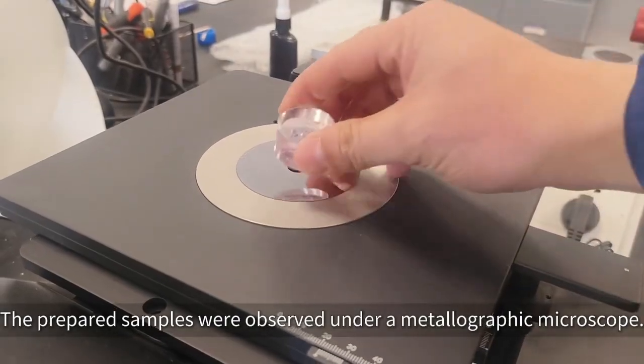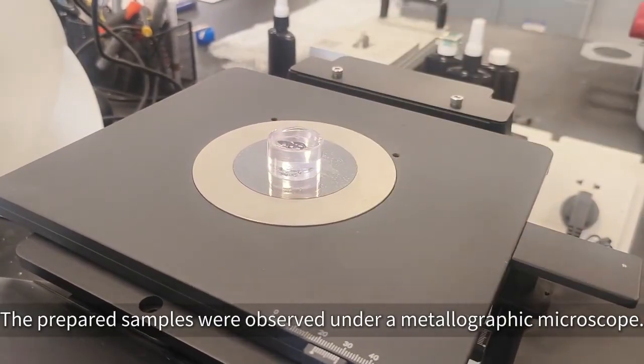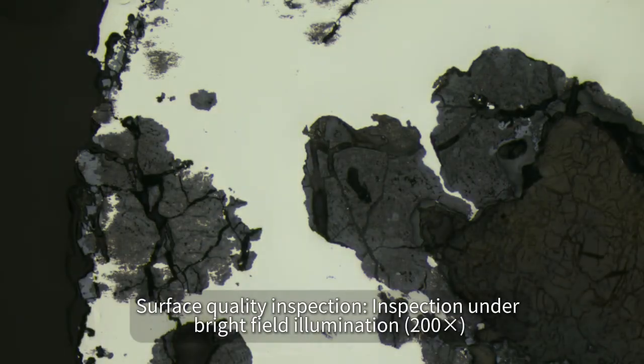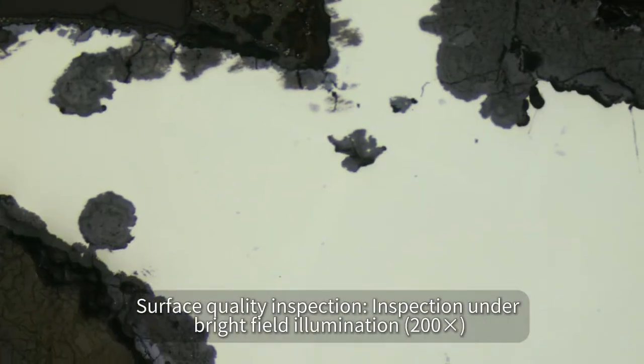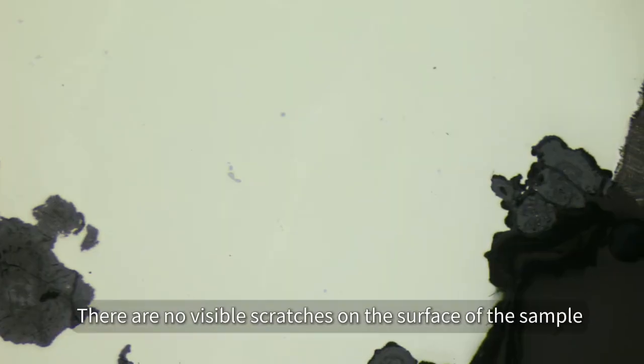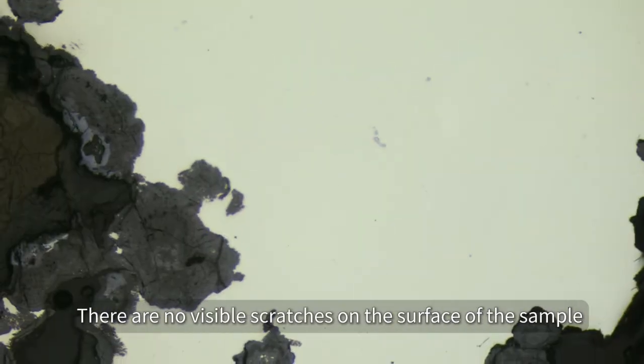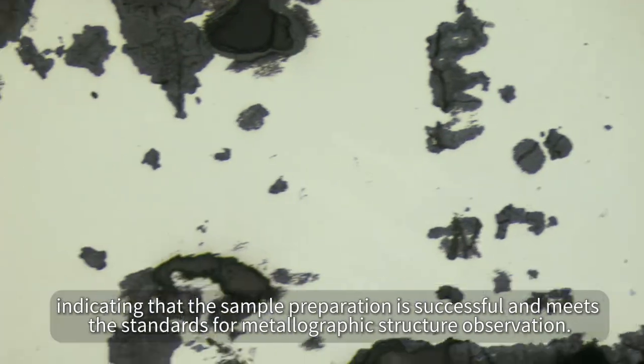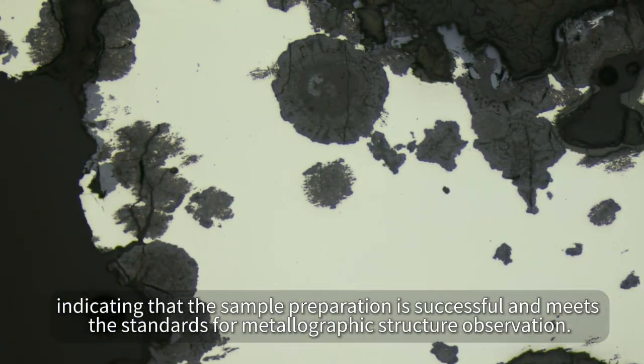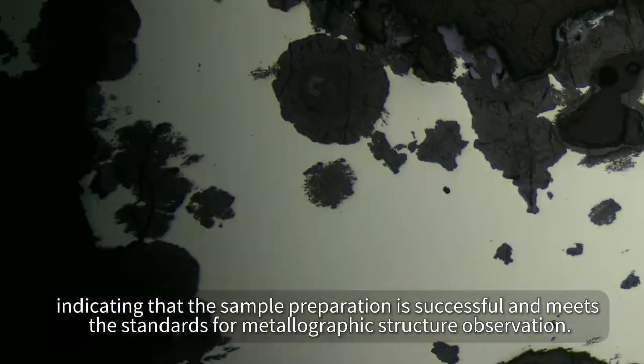The prepared samples were observed under a metallographic microscope. Surface quality inspection. Inspection under bright field illumination, 200x. There are no visible scratches on the surface of the sample, indicating that the sample preparation is successful and meets the standards for metallographic structure observation.